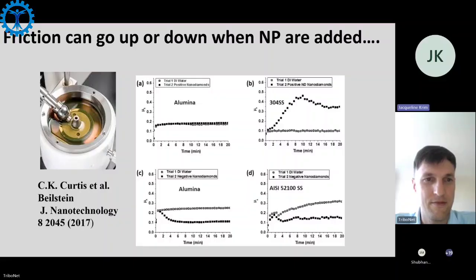So as we can see, we looked at alumina contacts and we looked at stainless steel contacts and positive nanodiamond treatments rendered no change for alumina contacts. They were disastrous for the stainless steel, causing a great increase in friction, and negative was beneficial in both cases. So we really need to know what's going on here. All right, next slide.